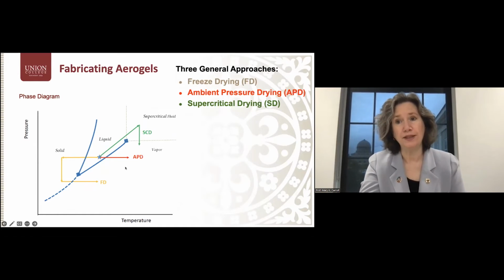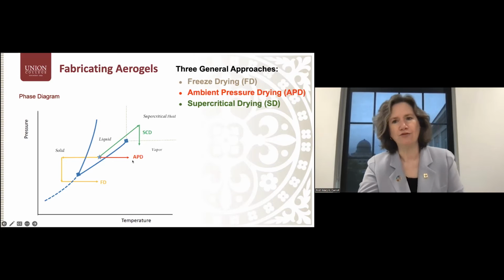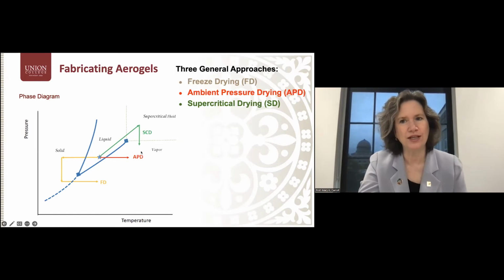Now, one possibility is to do a lot more chemistry and to surface modify the matrix so that it has very low surface tension. And so if we put some sort of agents on it so that it has extremely low surface tension, we can do ambient pressure drying, and you will still be left with an intact aerogel. This requires, as I said, more chemistry and a certain amount of patience.